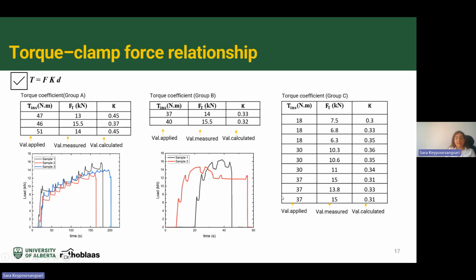We did the same thing for group C. I mean that we increased the torque continuously. In 3 samples, we increased the torque until 18 Newton meter. In 3 samples, we increased the torque until 30. And in 3 samples, we increased the torque to about 37, a little bit less than 37, because we don't want to have a failure in this group. And we found the torque coefficient. You can see that in these two groups, because we applied the torque in the same condition and with the same speed, the torque coefficient is kind of similar. It's around 0.33.